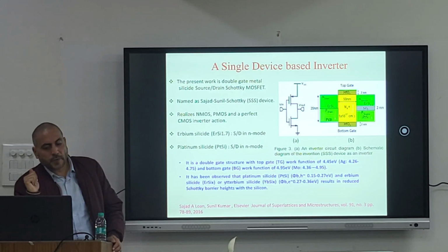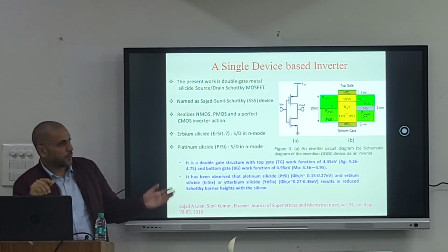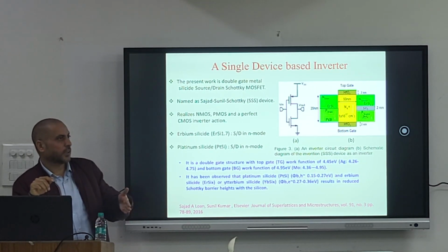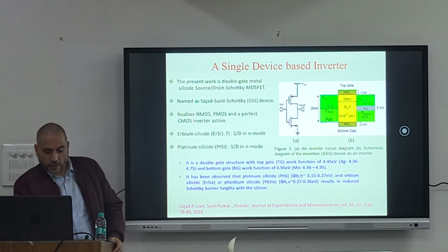Why do we use this erbium silicide and platinum silicide? What we have actually looked at. Again, we had a problem with this structure. It is the on current again, right? So if you see here, we have observed that platinum silicide and erbium silicide or ytterbium silicide result in reduced Schottky barrier heights with silicon.